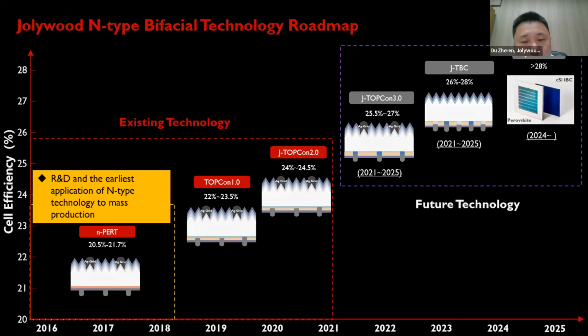In the future, we will continue to develop TOPCon 3.0 technology to reach more than 25.5% cell efficiency. With this new technology, the process steps will be further reduced. And we also reduce the silver consumption so that the cost will be comparable to PERC. And we will also develop new cell structures that have even higher efficiency potential. And we will achieve more than 26% cell efficiency by J-TBC structure. And this structure is a hybrid structure between the TOPCon and the IBC. Another future direction is going for tandem cell, and we expect more than 28% efficiency based on this structure. But this probably will be out in 3 years.